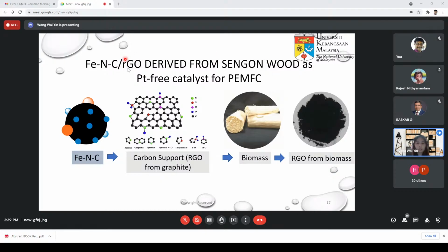And also we want a highly graphitic structure to be used as a support material. What we are also looking into is that biomass consists of a lot of impurities. These impurities may not be good because they create defect sites. For certain applications such as supercapacitors, you need a very smooth flow of electrons. But for fuel cell applications it's different, because when used as a catalyst support, we need more defect sites in order to anchor the catalyst particles on the surface. So this will provide more defect sites that allow the anchorage of the catalyst particles.